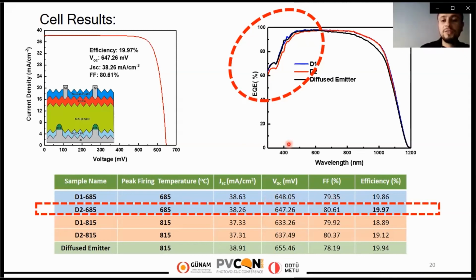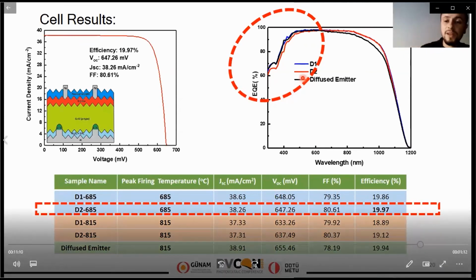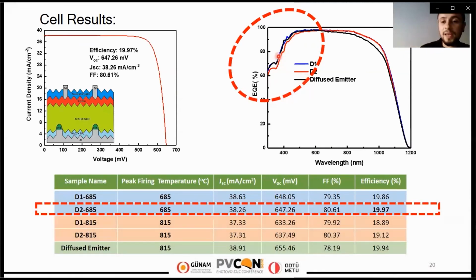And if you look at the EQE graphs on the right side here, the cell response to photons with short wavelengths is similar for diffused and implanted emitters, especially for D1. If you look at the blue and black curves, the blue stands for D1 and black stands for the diffused emitter with a sheet resistance of 100 ohm per square. They are very close. D2 is a little lower because the doping concentration is very high in the case of D2.